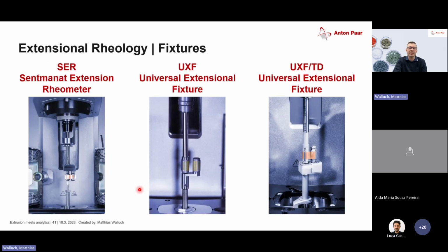For this kind of measurements, we offer 3 different measuring systems. So there's the standard one, the SER tool, which is the standard for many, many different other rheometer brands as well. And it is just 2 drums where you apply a sample, you close an oven, you melt the sample, and then you just turn here in one direction. And these 2 drums are connected via a gearbox, and the sample is just stretched in both directions, and you get basically the force that is needed to tear the sample apart. And this can then be used to calculate the extensional viscosity.